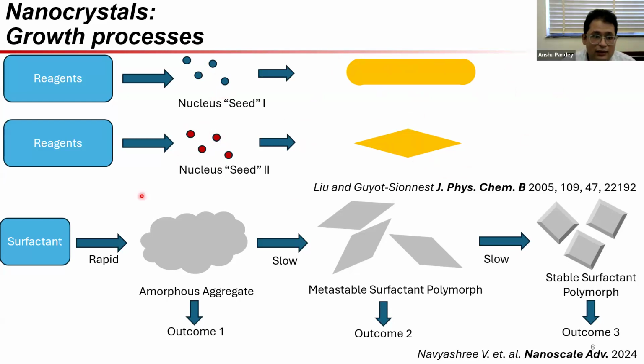In our own work very recently, something related but much stranger was observed, which was that not just can this happen with the main material that you're interested in, this can happen with the participating reagents. In this particular example, what we found was that when we use certain classes of surfactants, under reaction conditions they tend to form aggregates. If we intercept this and do a reaction at the time of formation of this amorphous aggregate, we get one set of outcomes, not necessarily very desirable, but anyhow, a certain outcome. If we, however, move on and allow, after some time, this metastable surfactant polymorph to form, we would get a totally different reaction outcome, which in this case was our desirable one.